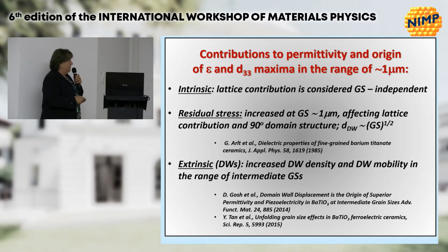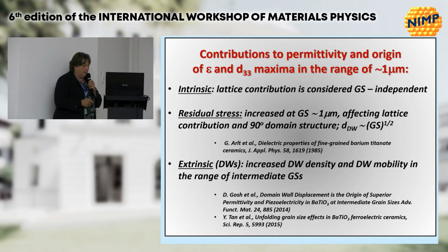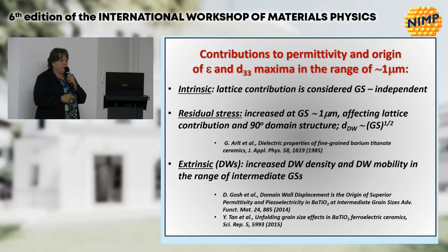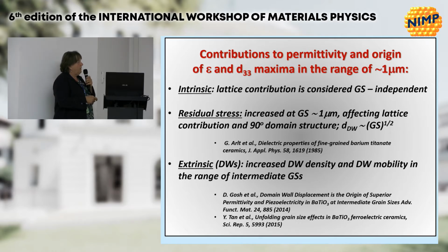Then there was the interpretation of Arlt and Hennings in the 80s. Mostly Arlt performed some studies. According to him, the fundamental role in this maximum is given by the residual stress contributions that are somehow maximized around this grain size, due to the fact that at this level of grain size in barium titanate ceramics, the arrangement of 90-degree domain walls is favorable, due to the dependence of domain wall length on the grain size that was confirmed by this law.